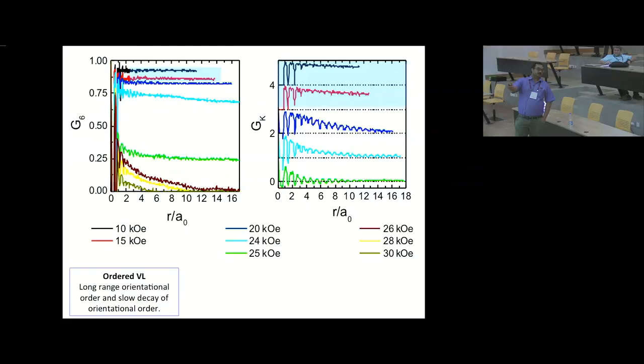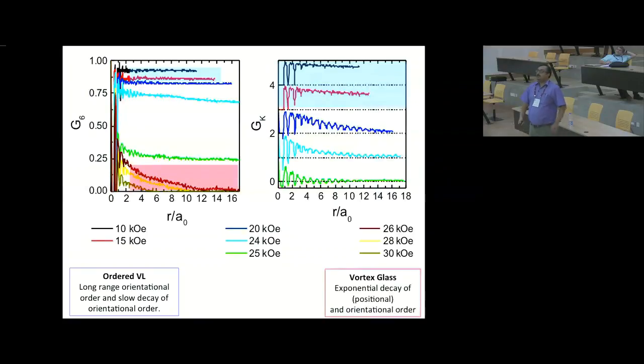We have a long range orientational order. The positional order seems to be slowly decaying. It could be a quasi long range positional order, but we cannot really find the functional form because here we don't have enough range. At low fields we have fewer vortices. At high field, which is above the peak of the peak effect, when we have disclinations, we have a vortex glass, and here both positional and orientational order decay exponentially.